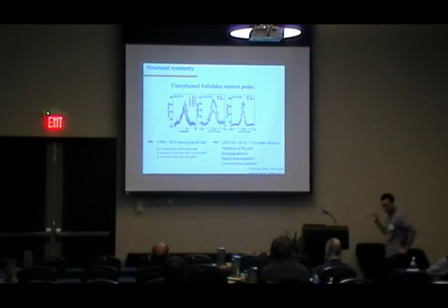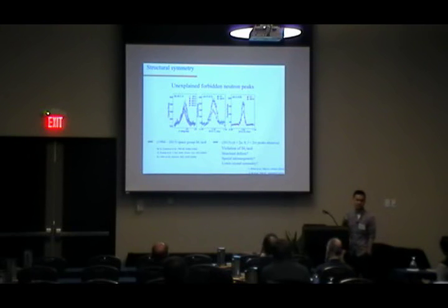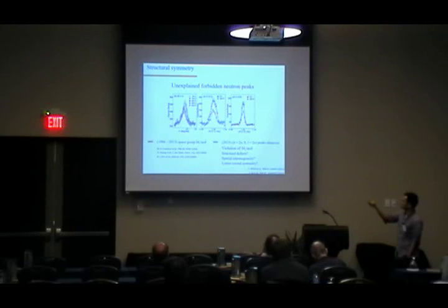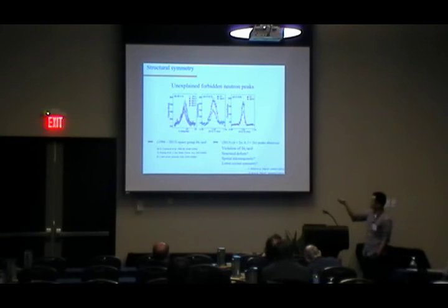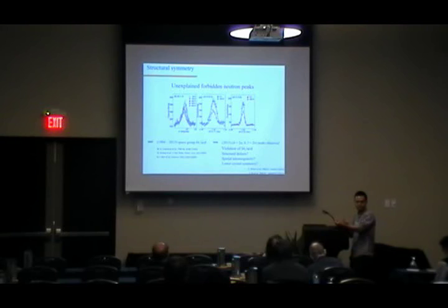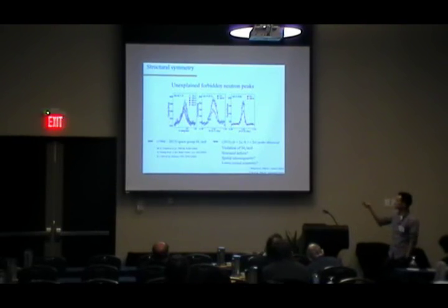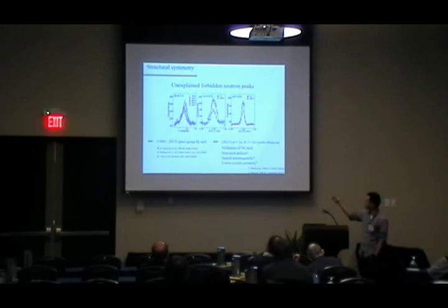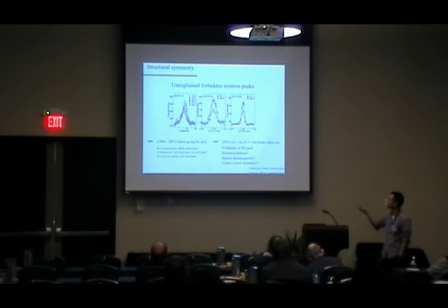Let me start off by doing an exercise on this Sr2IrO4 sample, namely by first resolving its crystallographic structure. Up until about 2013, this was the tetragonal space group considered correct for this compound. Towards the end of 2013, some more careful neutron diffraction studies revealed Bragg peaks that were forbidden within the space group. There was some confusion about whether the space group might be incorrect, or whether this was due to defects, parasitic phases, and so forth.